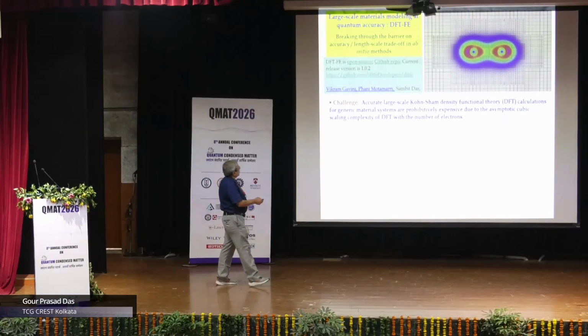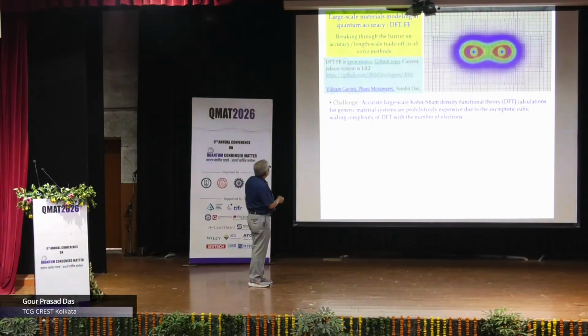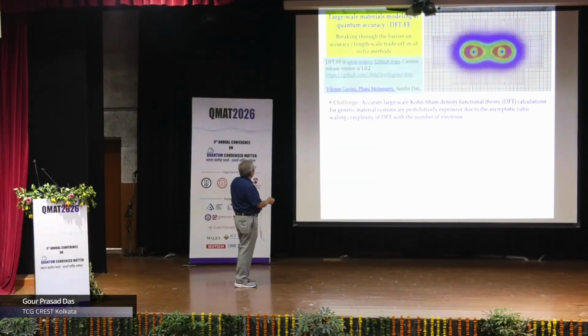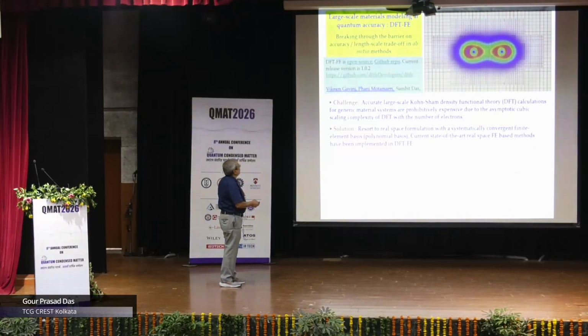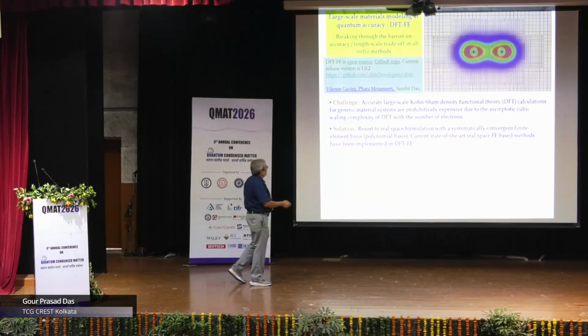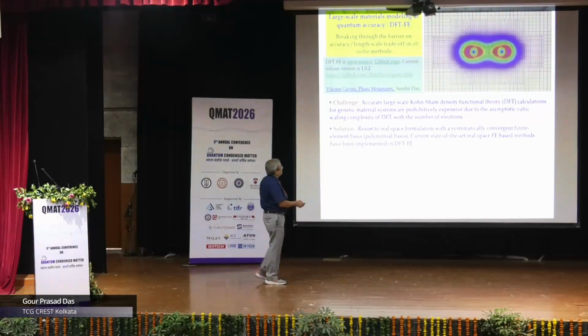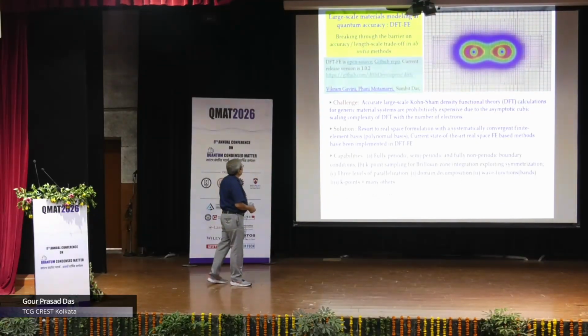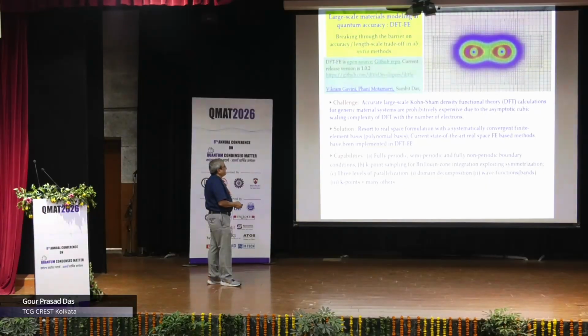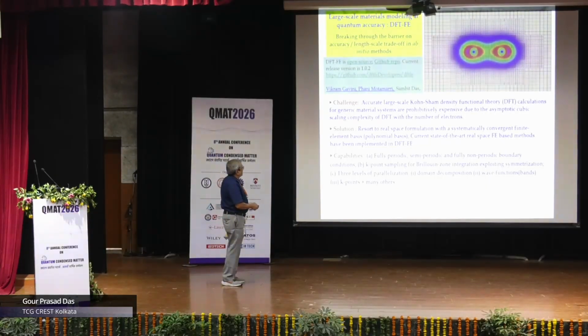accurate large-scale Kohn-Sham density functional theory calculations for generic material systems are prohibitively expensive due to the asymptotic cubic scaling complexity of DFT with the number of electrons. The solution is to resort to a real space formulation with a systematically convergent finite element basis. Polynomial basis we do it, okay? So the current state of the art real space finite element based methods have been implemented in DFT-FE. And the capabilities of this are really impressive. It can handle fully periodic systems.